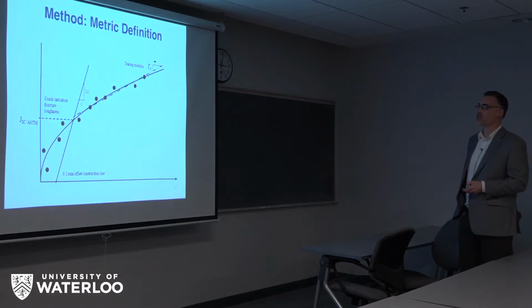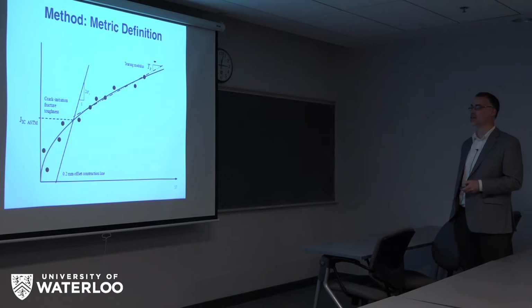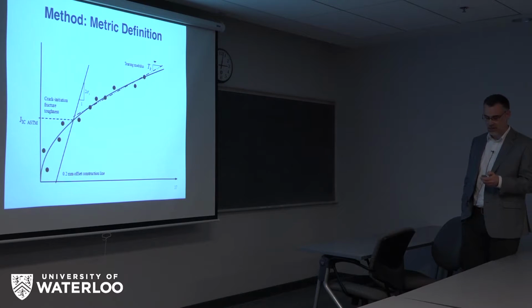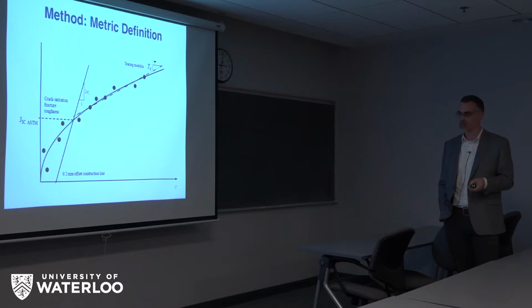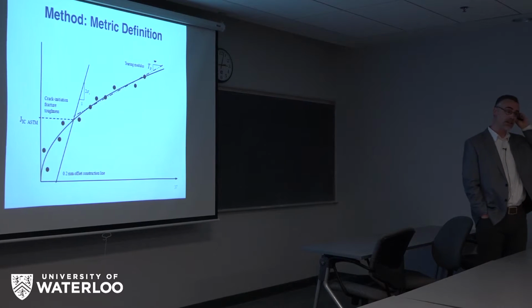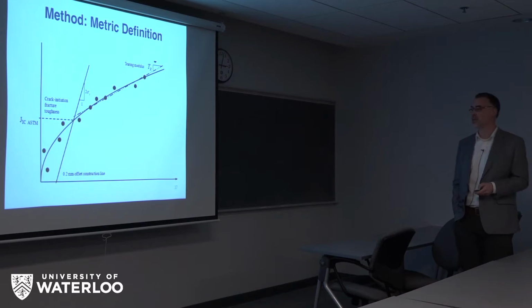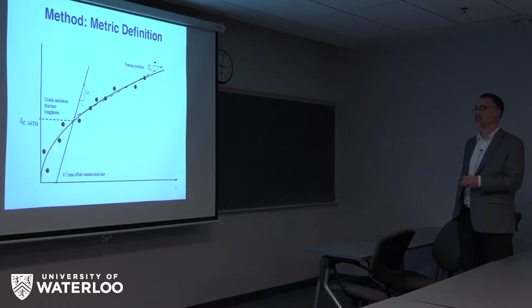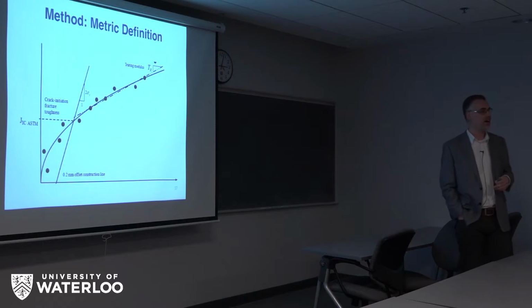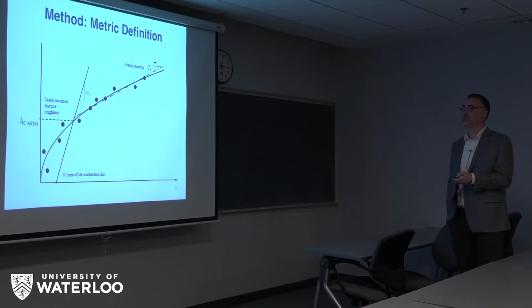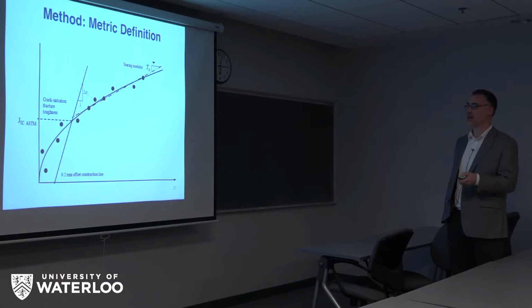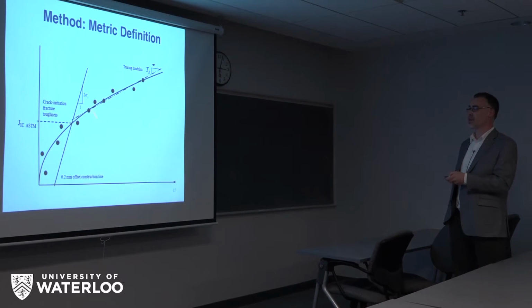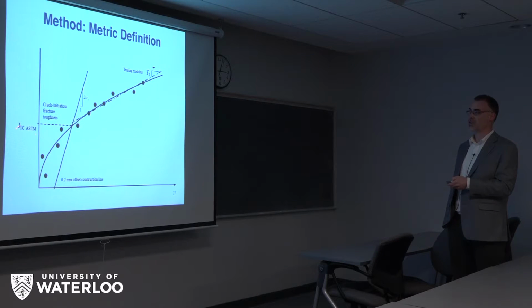And so from our JR curves, we needed some metrics, and today I'm just going to talk about J1C mostly. So that's the detectable crack growth initiation fracture toughness. An ASTM standard that's used quite widely in this field is called E1820, and it tells us to use an offset line. This is mainly just to make sure it's detectable by other techniques that we're not using, because bone doesn't behave like metal, basically. And so we define this metric as our crack growth initiation fracture toughness according to ASTM.